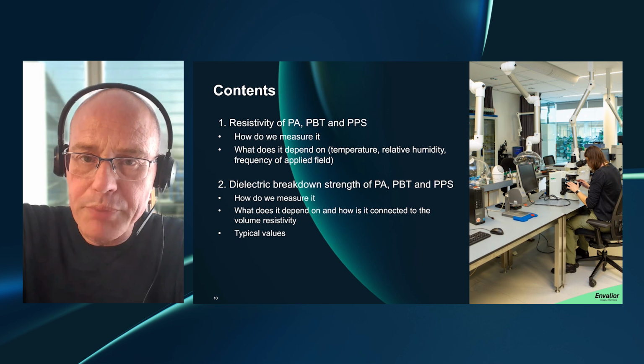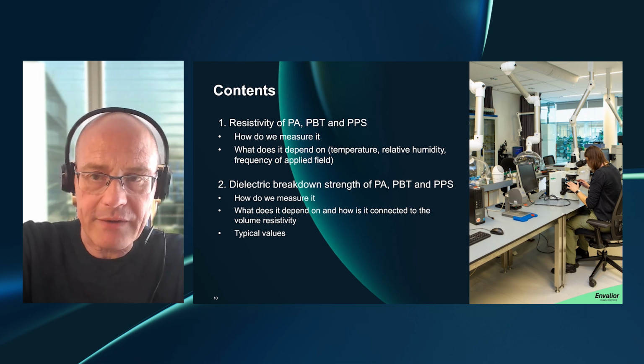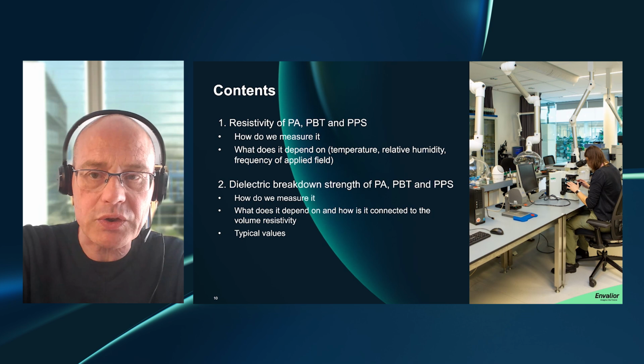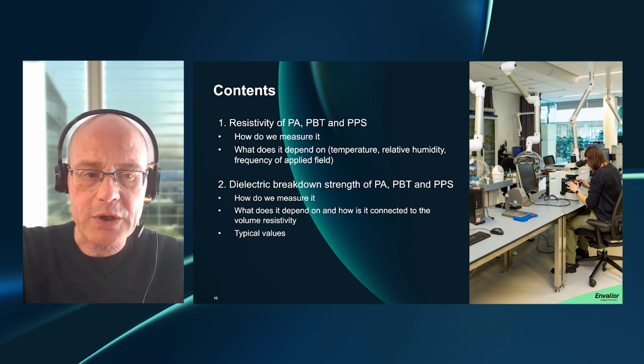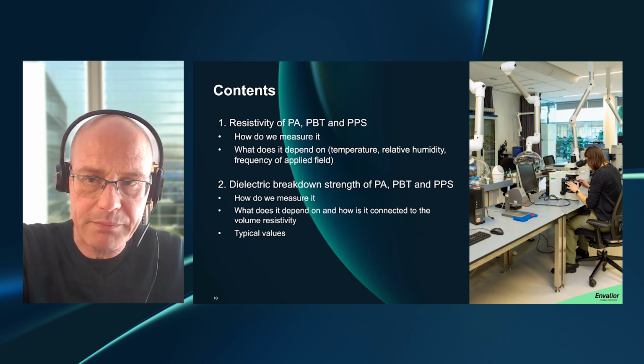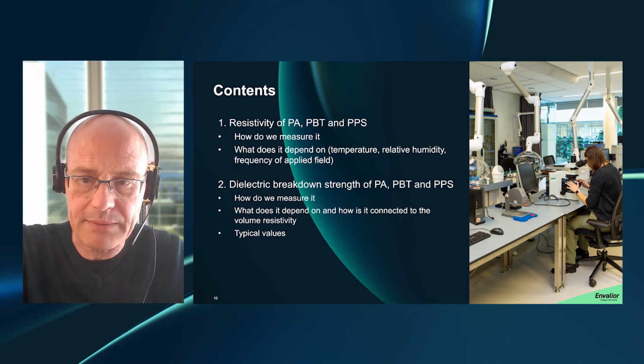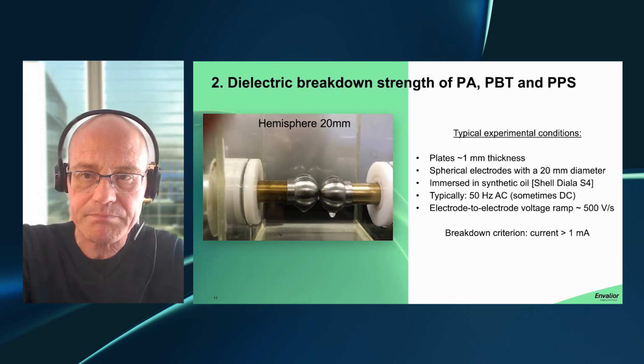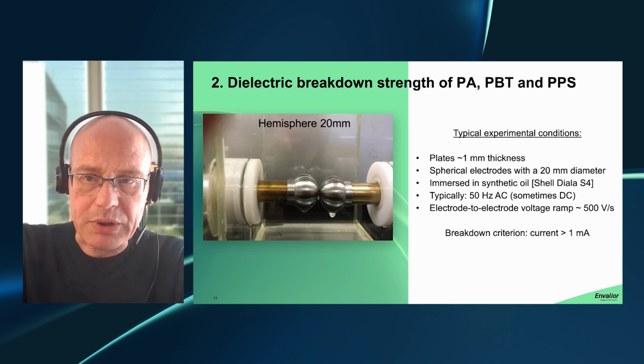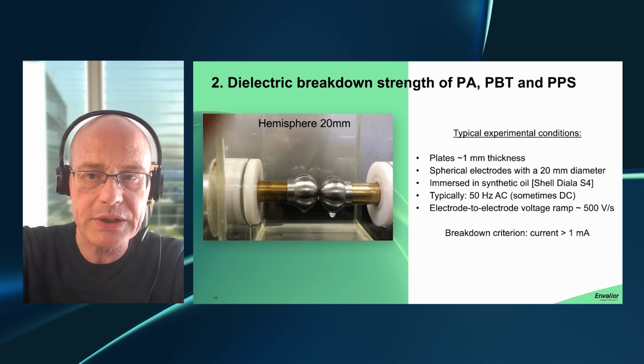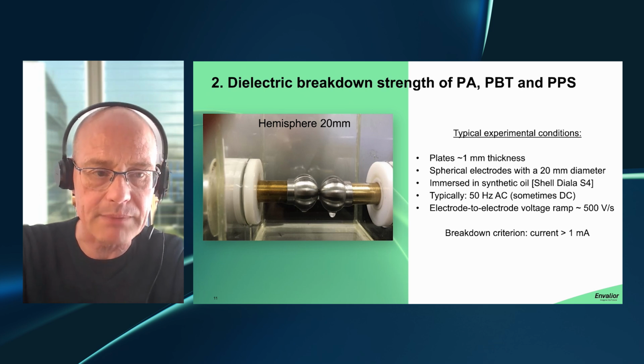And this now brings me to the second paragraph on the dielectric breakdown strength of the polyamide, PBT and PPS. Let me first briefly explain how we measure it, and then we try to connect this information to the previous paragraph on resistivity. So here you see a typical setup. On the left, you see two hemispherical electrodes with a diameter of 20 millimeters, which is typical. We have other electrodes too.